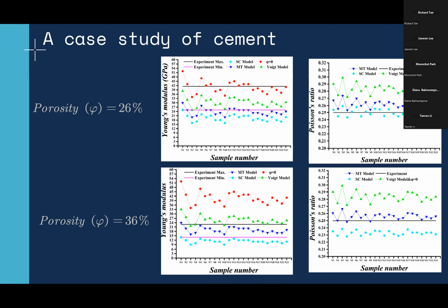As you can see, the Young's modulus results obtained using the Voigt and the MT method are closer to the experimental result. However, the Poisson's ratio results obtained with the SC method are closer to the experimental values for low porosities, and the results obtained using the MT method are closer to the experimental ones for higher porosities. So those discrepancies demonstrate that the current method is not suitable for amorphous materials, and the mechanical properties of CSH could not directly derive from those equations.